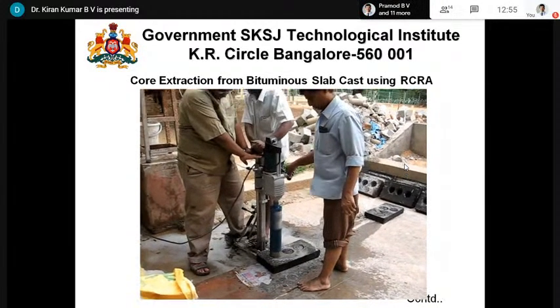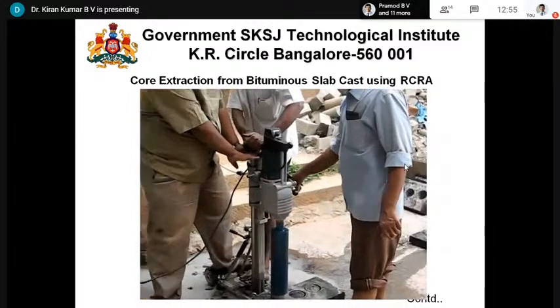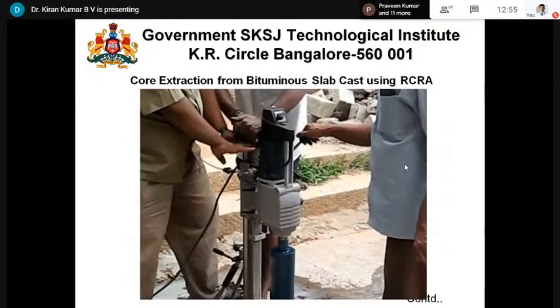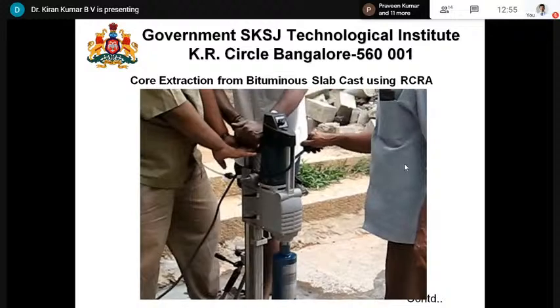This video shows many slabs taken at the laboratory level to understand, just to show you the slab which has been prepared, and then we have taken out that particular material to justify the codal values. Even the mix design done using recycled asphalt, with lesser binder content and 8% of plastic additive, gives the same properties we were getting with the earlier hot mix asphalt. We showed that at the laboratory level, before going for the trial stretch, we have done that work. So the cores are drawn.